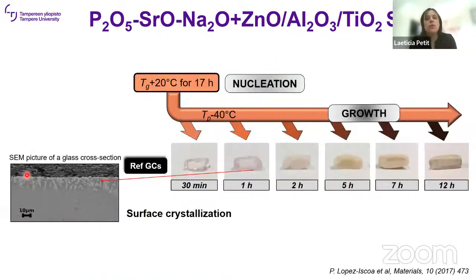So we try to do some glass ceramic. So it's to in situ grow crystals in the glass. So we use a two-step process. The first one is the nucleation. So we do a heat treatment around the glass transition temperature for 17 hours. And then we increase the temperature near the crystallization temperature to grow the nuclei into the crystals. And then we look, of course, at the cross section of the glass.